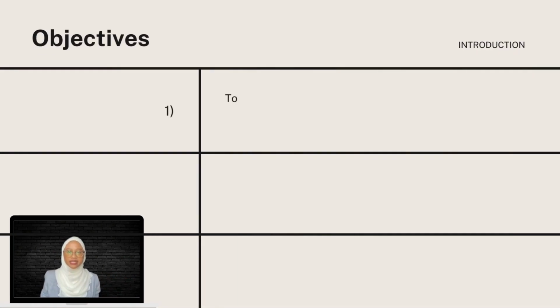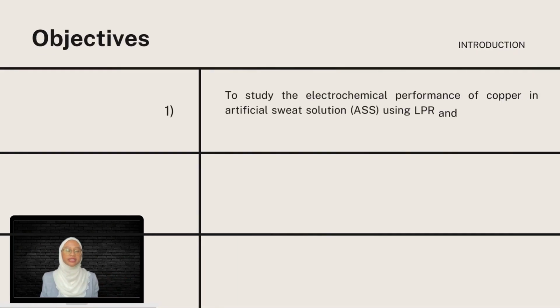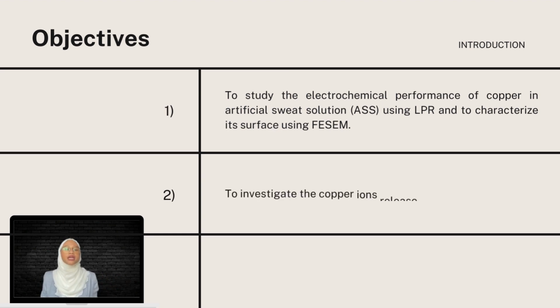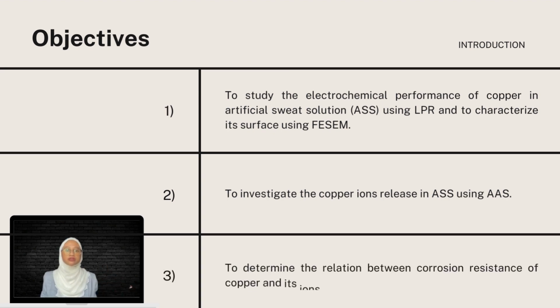First, to study the electrochemical performance of copper in artificial sweat solution using the linear polarization resistance method, and characterize its surface morphology using field emission scanning electron microscopy. Second, to investigate the copper ions released in artificial sweat solution using atomic absorption spectroscopy. And lastly, to determine the relation between corrosion resistance of copper and its ion release with 3 immersion times.